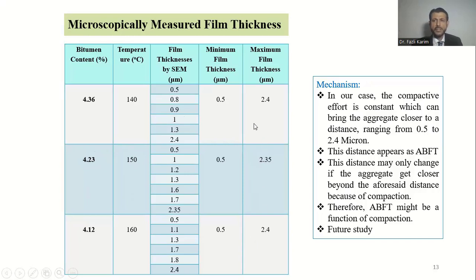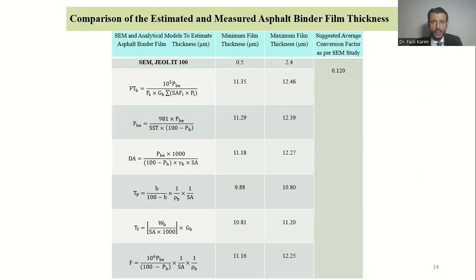And these film thicknesses can be trusted because the images are very clear and indicate what really happens in the sample and what is the possible range of binder film thickness. Now, there is a hell of a difference between these values. The micro-based film thicknesses basically vary from 0.5 to 2.4, where the film thicknesses based on analytical models range from 9.88 to 12.46. So there is a huge difference.